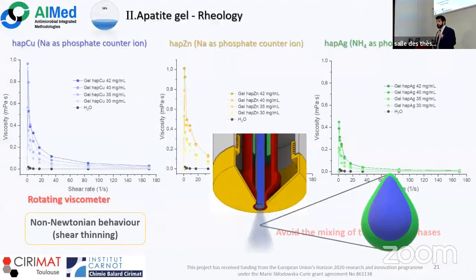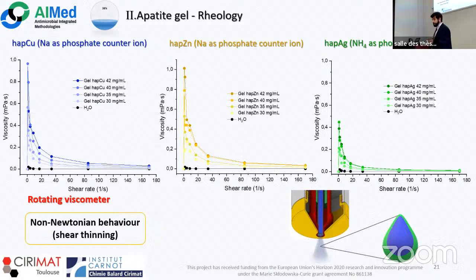this process, we did some viscosity measurements on the gels that we prepared with a rotating viscometer. And we noticed for all the gels a non-Newtonian behavior, that is shear thinning, that already suggests that the nanocrystals present in the gel have interactions with one another, because otherwise we couldn't see this kind of behavior. And we also noticed that the copper and the zinc physical gels at the same concentration had more or less the same order of values of viscosity.